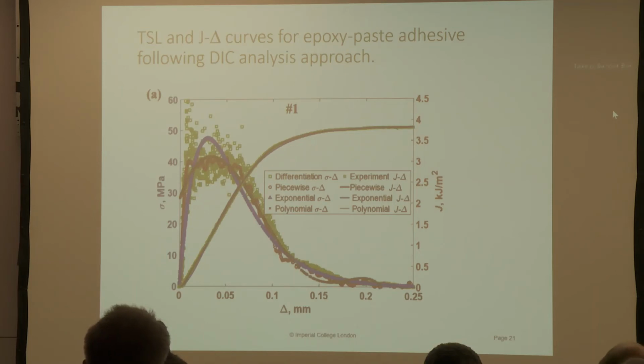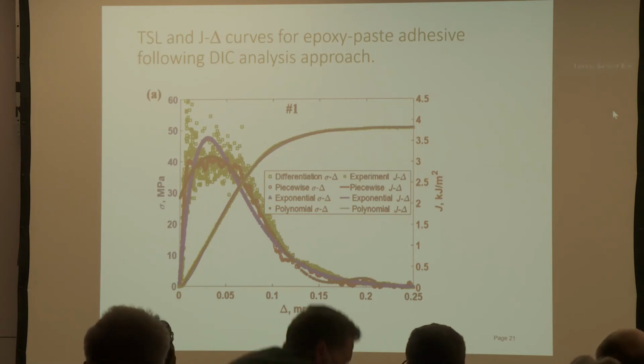So this is some data that we had for one particular adhesive. This was an epoxy paste adhesive, where we've used digital image correlation, and we've developed the relationship between J and the displacement delta, in this case, the opening displacement term, and using different schemes for controlling that relationship, then we can determine the traction separation law. So we can think in this case of the direct differentiation of the stress displacement function as being like the experimental value, and then we can apply different techniques to simplify that. So this is quite an interesting approach. I know many groups are using DIC and extracting traction separation laws and J simultaneously in this way.